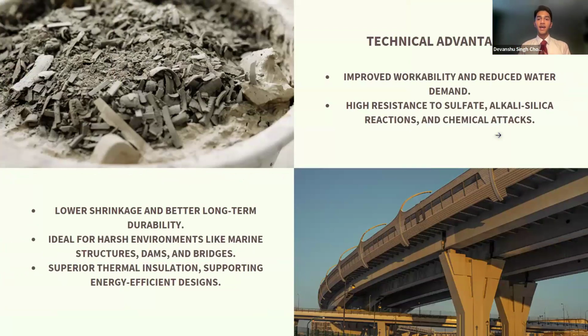Some of the technical advantages of using fly ash in concrete are a proven improved workability and reduced water demand due to the lower hydration heat, which in turn leads to a densely packed matrix which resists sulfate and alkali silica reactions and also resists chemical attacks such as chloride ingress and carbonation in the concrete. The lower heat of hydration also gives a lower shrinkage property, which in turn yields better long-term durability. This tightly packed matrix is ideal for harsh environments as it does not let the moisture in the air permeate and introduce cracks. It is very good for marine structures, dams, and bridges. And the superior thermal insulation provided by the fly ash is very efficient in providing a more stable interior environment.